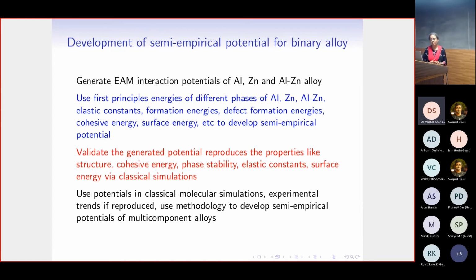And what is the data we are going to look at? The energies of the different structural phases, the elastic constants of these phases, the formation energies if we are working with binary alloys, the defect formation energies, cohesive energies, and all these things we will put into the fitting procedure for the semi-empirical potential. Then whatever potential we generate, we want to validate that it produces all the physical properties correctly.